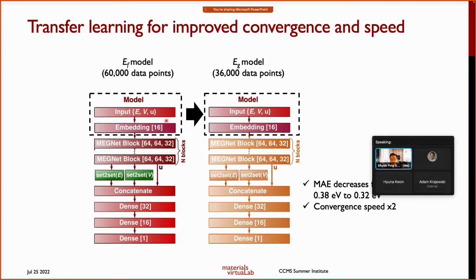So what we found was that if you actually just take the embedding vectors from our formation energy model, which has the most data points, and we just reuse those embedding vectors, we don't actually retrain them, and we just build a new MEGNet model using the same embedding vectors for the band gaps, we can actually decrease the mean absolute error of our band gap from 0.38 eV to about 0.32 eV, and it also converges a lot faster. In other words, just by doing this kind of transfer learning, using models that have already been built on a very large data set, we can actually significantly improve the model performance on a smaller data set.